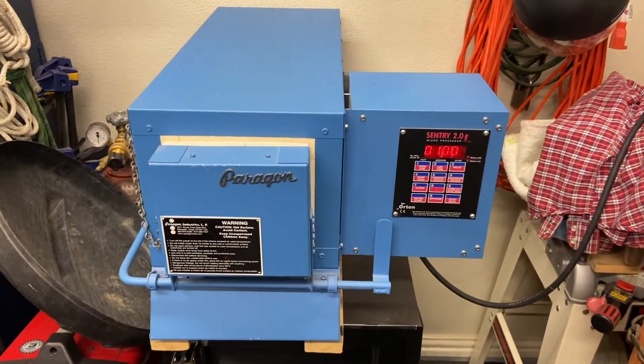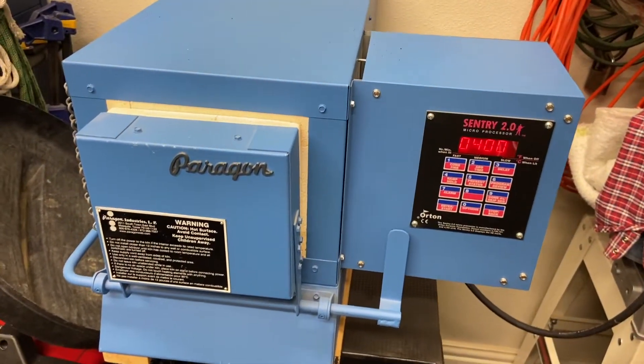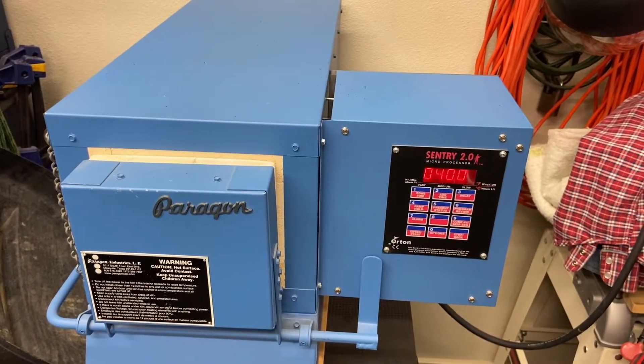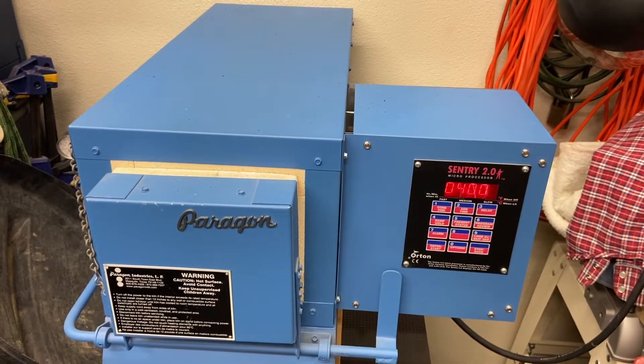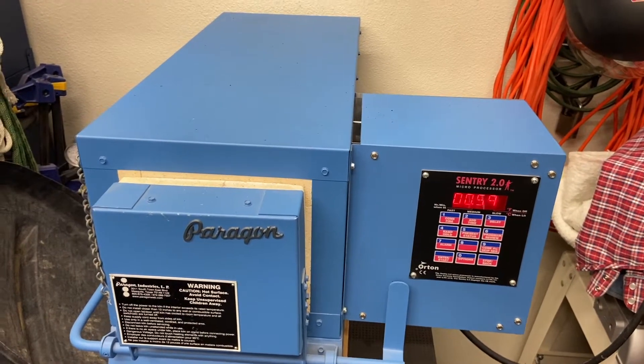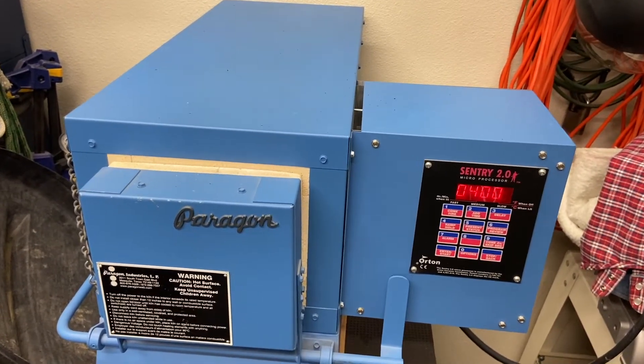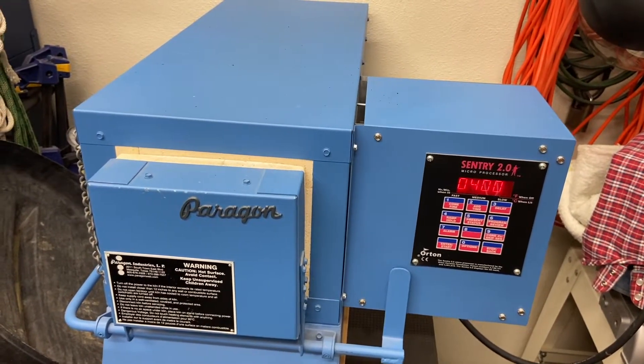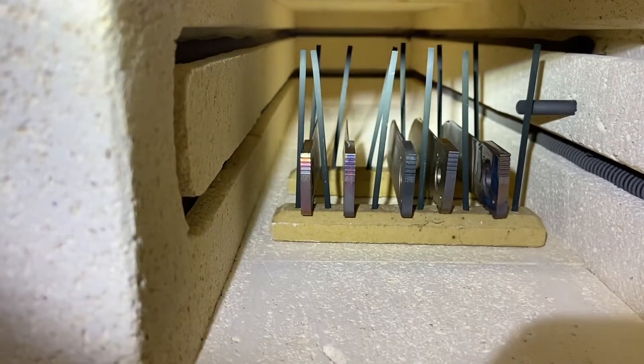The last thing I have on the go is the other five blades to go with those finished handle slabs. I already heat treated them the other day — this time I went ahead and did the plate quenching. I had a vise set up and used two aluminum plates, pinching the blades between those after they came out of the heat to cool them. I think I like it. I took somebody's advice on trying plate quenching instead of just air quenching or hanging them up open air — I think the plates work pretty well. Right now those are in there for their first temper. I'll pull those out in another 59 minutes.